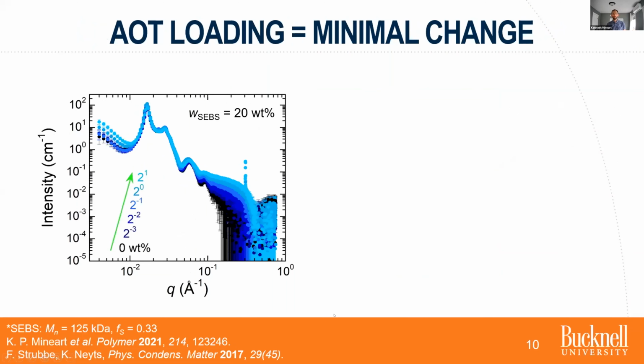And so we can vary the amount of AOT to get a better understanding of what's going on in these systems. Again, fixing the triblock copolymer concentration and varying the amount of AOT as indicated on the bottom left here. Again, a lot of these features that arise from the block copolymer, which I'll come back to, remain basically the same. And we see this plateau that I mentioned before lifting more and more with AOT concentration out to the left. And so we can model these things, and basically we model them as a set of two kind of bidispersed spheres, one that owes to the polystyrene end block domains and one that corresponds to the AOT reverse micelles. When we do that, we get really nice fits for the most part.